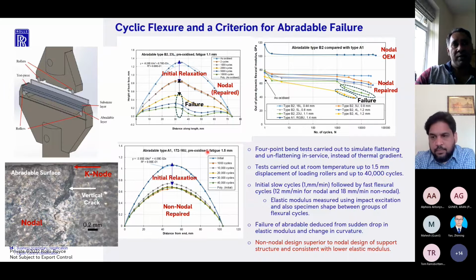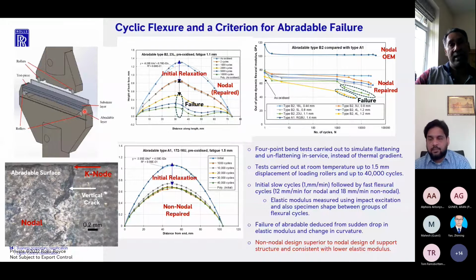We did interrupted tests. We applied a certain displacement, did a number of flexural cycles, typically of the order of 10,000, took the specimen out, inspected it for cracks, put it back in again, and then repeated, going to a higher number of cycles at a given displacement. So we did a number of tests.